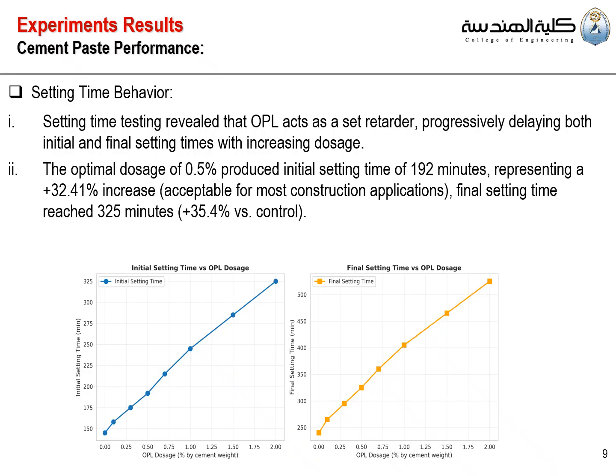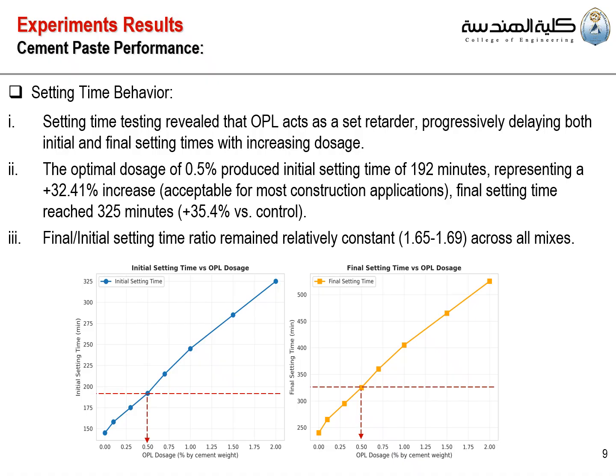So what we can see is that we have an optimal dosage at 0.5%, producing an initial setting time of 192 minutes. It represents a 32.41% increase. This is very acceptable for most construction applications. And the final setting time reached 325 minutes, an increase of 35.4% versus the control sample. The final to initial time ratio remained relatively constant. We have to point out this thing. It is 1.65 to 1.69 across all mixes.